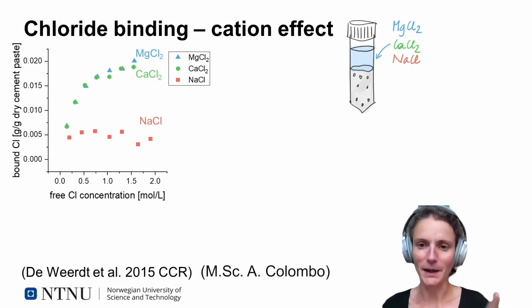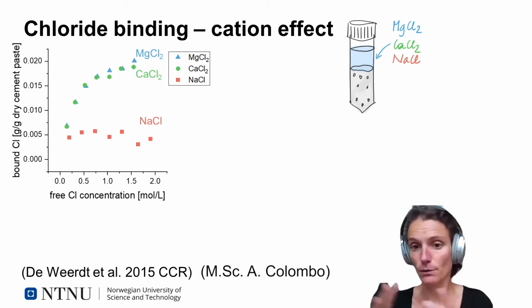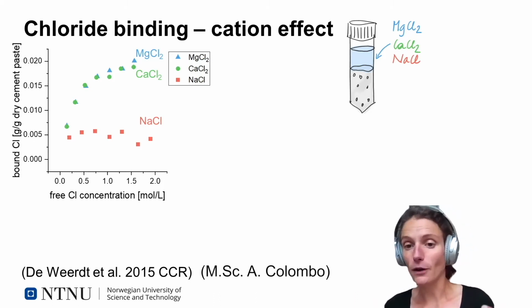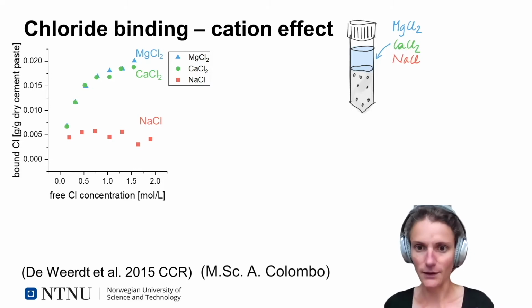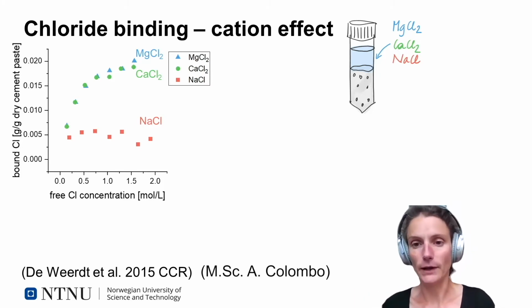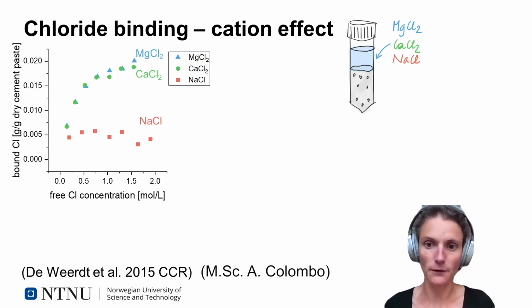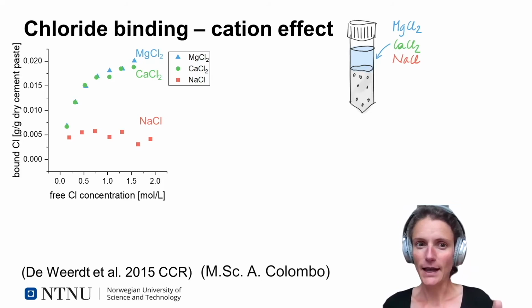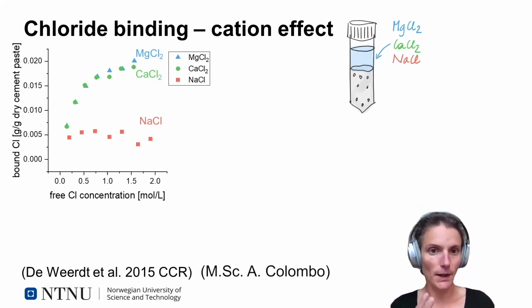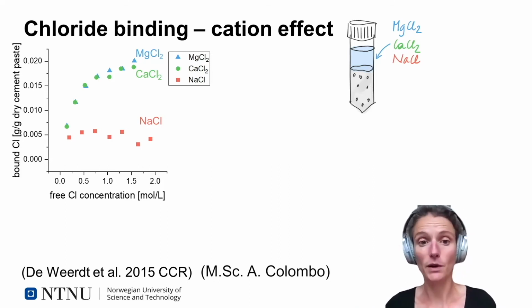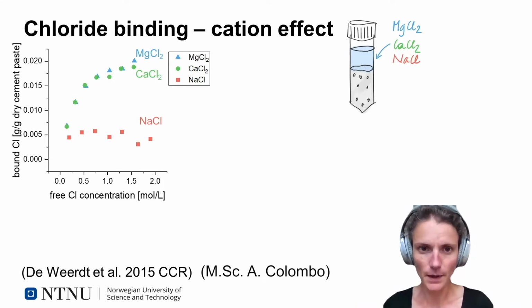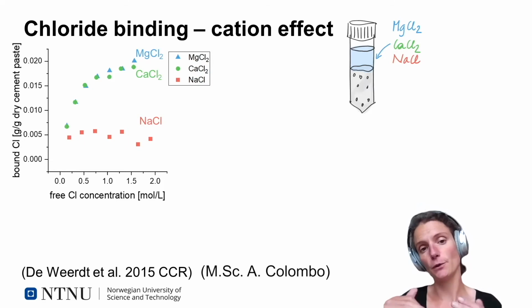On the left, we see binding isotherms. So in the binding isotherms, you plot the amount of bound chlorides per gram cement paste as a function of the chloride concentration it's exposed to. In this case, the chloride concentration at equilibrium. And you can see that we expose the cement paste to a range of chloride concentrations. So we go from approximately 0.25 mole per liter up to 2 mole per liter. Typical chloride concentration for the Atlantic Ocean is about 0.5. So it means that, for example, 1 or 2 mole per liter are high concentrations and are more relevant for, for example, de-icing salts.